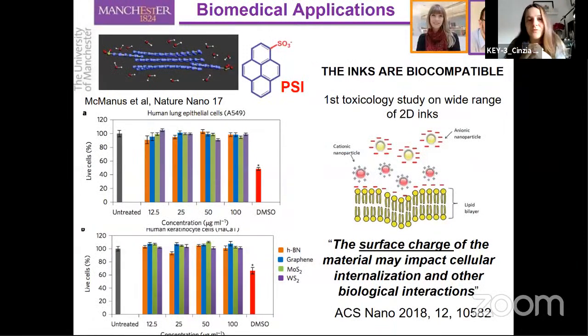And in the last few minutes of my talk, I want to move into biomedical applications. Indeed, I told you at the very beginning that we didn't want to use NMP because it's toxic. But at the end of the day, you can see that we have used many additives in our ink, and in particular, we have used pyrene derivatives, and small aromatic molecules are very well known to be toxic. And therefore, we decided to perform a cytotoxicity test. This was done in collaboration with Kostas Kostarelos at the University of Manchester, and so the inks were exposed to 2 cell lines at different doses, and the results indicated that basically all the inks, no matter the 2D material that we consider, are actually biocompatible.